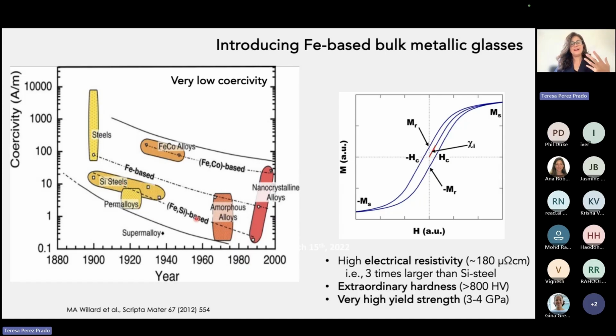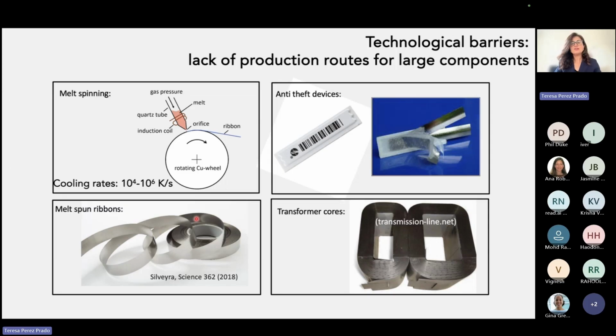And also they have extraordinary hardness. Of course, structural properties are not the main focus of these components, but of course we always want components that are robust and that they can handle the stresses under operation. So at this point, you might be thinking, well, if these materials are so great, why are we not using them already? And the reason for this is that there are very large technological barriers to make large components with these materials, because in order to stabilize this amorphous structure, we need to cool them very fast from the liquid state. And the cooling rates that are required are of this order, 10 to the 4, 10 to the 6 degrees per second. This is extremely high and is not possible with most manufacturing methods that are available.